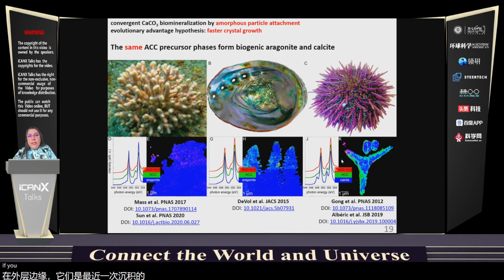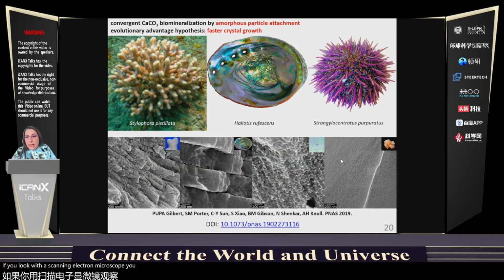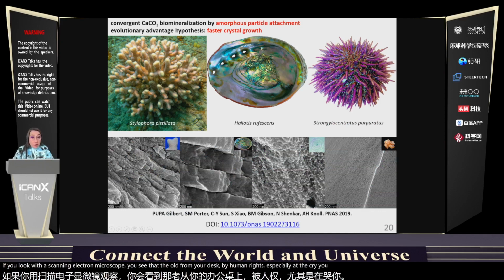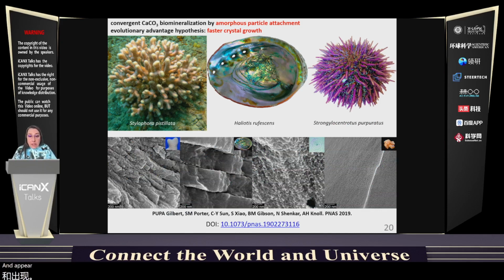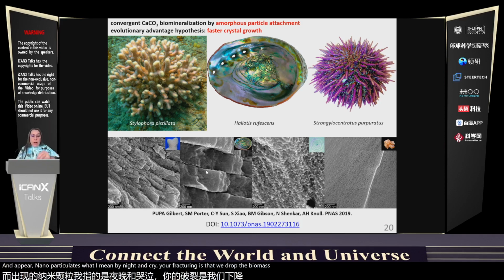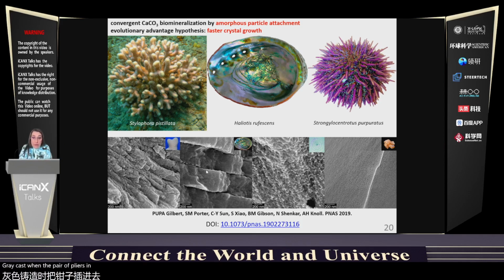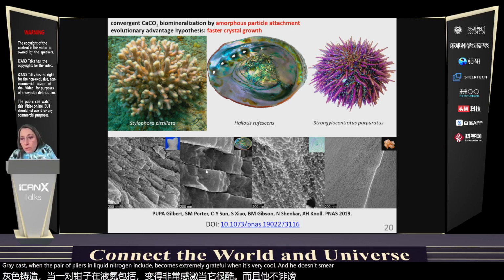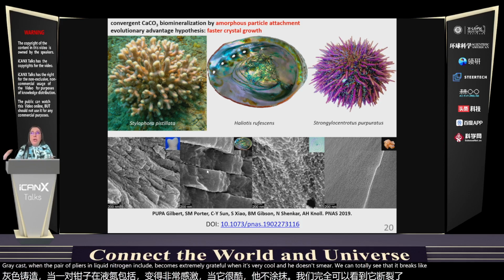If you look with the scanning electron microscope, you see that all three of these biominerals, especially after cryofracturing, appear nanoparticulate. What I mean by cryofracturing is that we drop the biomineral in liquid nitrogen, break it with a pair of pliers in liquid nitrogen, so it becomes extremely brittle when it's very cold and it doesn't smear. We can totally see that it breaks like cement would. So it's formed by an aggregate of nanoparticles, and then space is filled by ion growth.